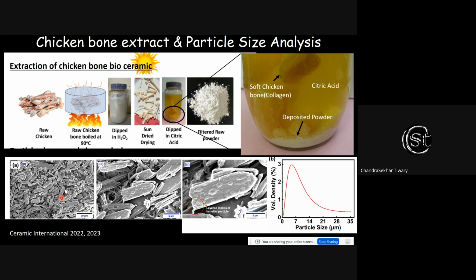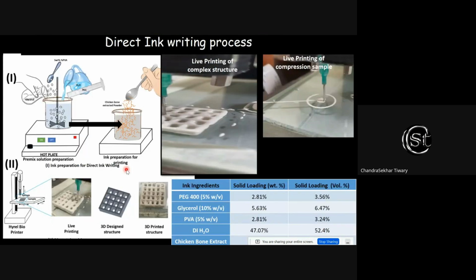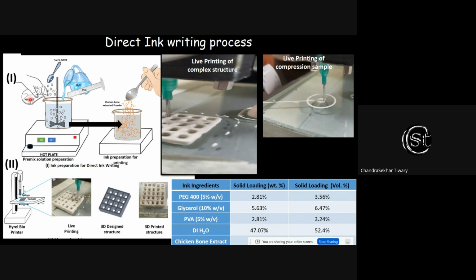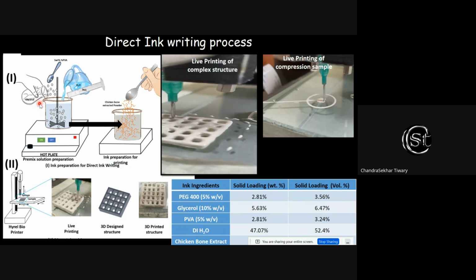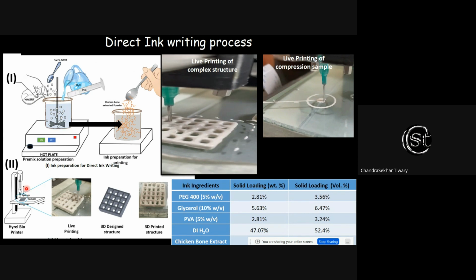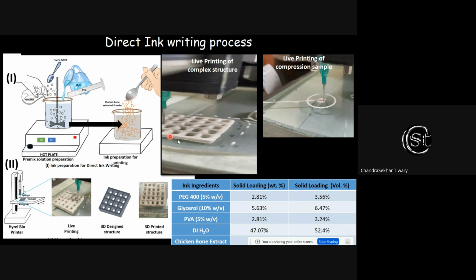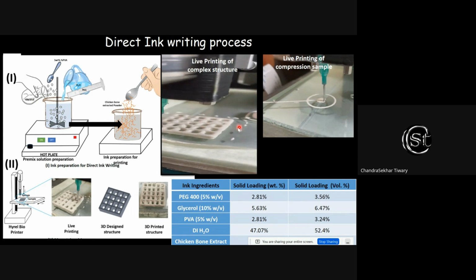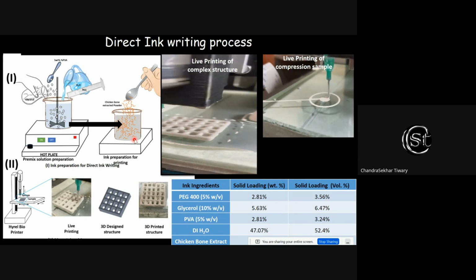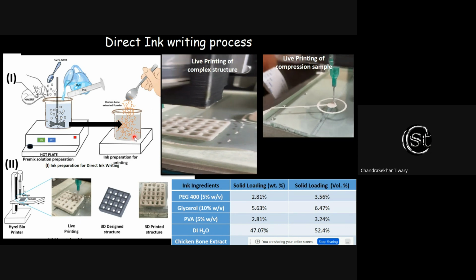If you look at it in a scanning electron microscope, you can see these nicely flat particles, which are very interesting. They are made of calcium. They have a very narrow size distribution, and we utilize them to make the ink. Now, once you make the ink with the right amount of binder and additives, this ink can be utilized for 3D printing. You can see here we can 3D print complex shapes, and we can optimize the chemistry, print in any possible shape, and utilize their mechanical property.